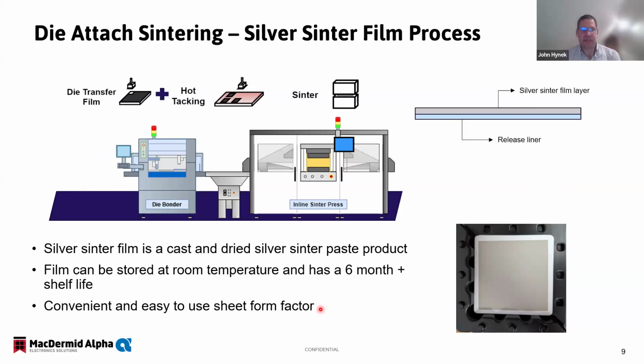This is die attach sintering. You can see here an example of the operation, and it's a lot less complicated than paste. Essentially, you're doing what we call our die transfer film operation. So you're taking the die, transferring the silver sinter film onto the back of the die, then placing that die on your substrate at elevated temperature, typically about 150 C. Once that's completed, you populate as many substrates as your sinter press can hold and send them into the sinter press. The sintering operation is done, and your package is sintered. Then it can go on to the next operation.